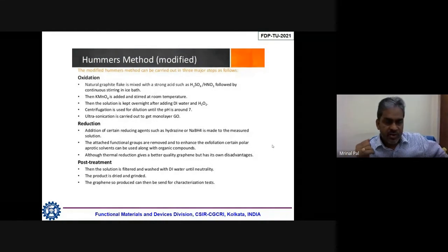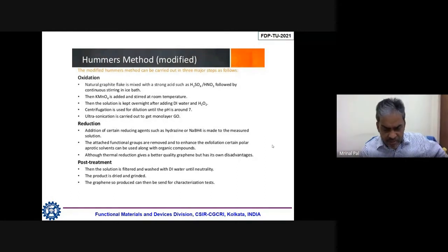Nowadays, GO, graphene oxide, is very famous. So from GO, if you wanted to prepare graphene, rather I must say reduced graphene oxide, RGO, then you have to reduce this using some kind of chemical solvent with reduction power, like hydrazine or sodium borohydride, NaBH4. So using that, you can do the reduction process, and ultimately you will end up with RGO, called reduced graphene oxide. This process is a little bit cumbersome, and it needs some low temperature.